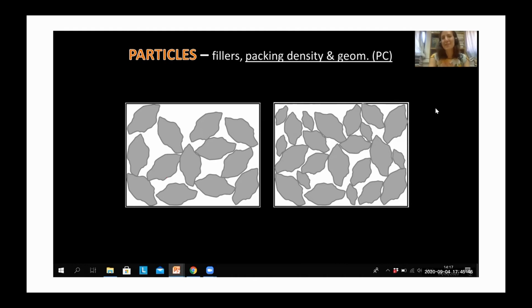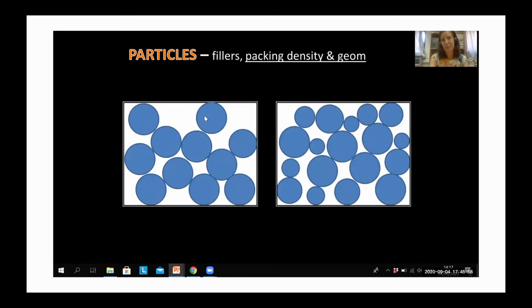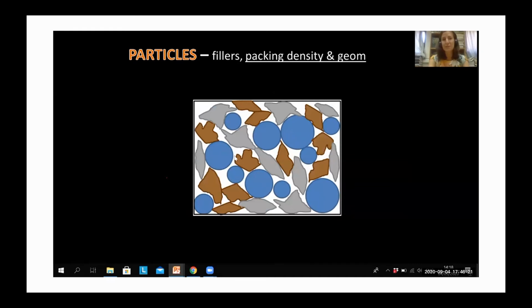So of course, there are still spaces which are left, and this is normal. But the packing density is much better and much more efficient. And the same happens if we have particles which are round. So here we can see the space filled just with particles of the same size. And here we can see particles of different sizes. And you can see again that in this case, the packing density is more efficient. What's the best in terms of packing density and geometry? The best is when we have different particle size, but also different particle shape. So when we put together aggregates which are round, but also angular or different sizes, we have a very good and efficient use of the space, let's say.